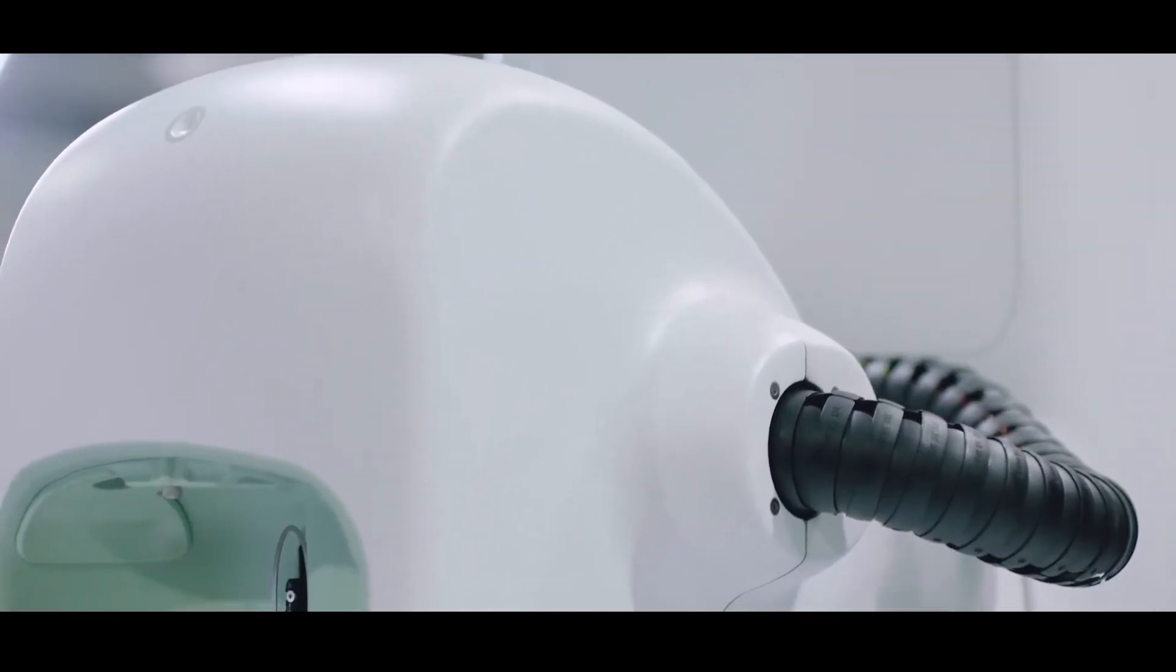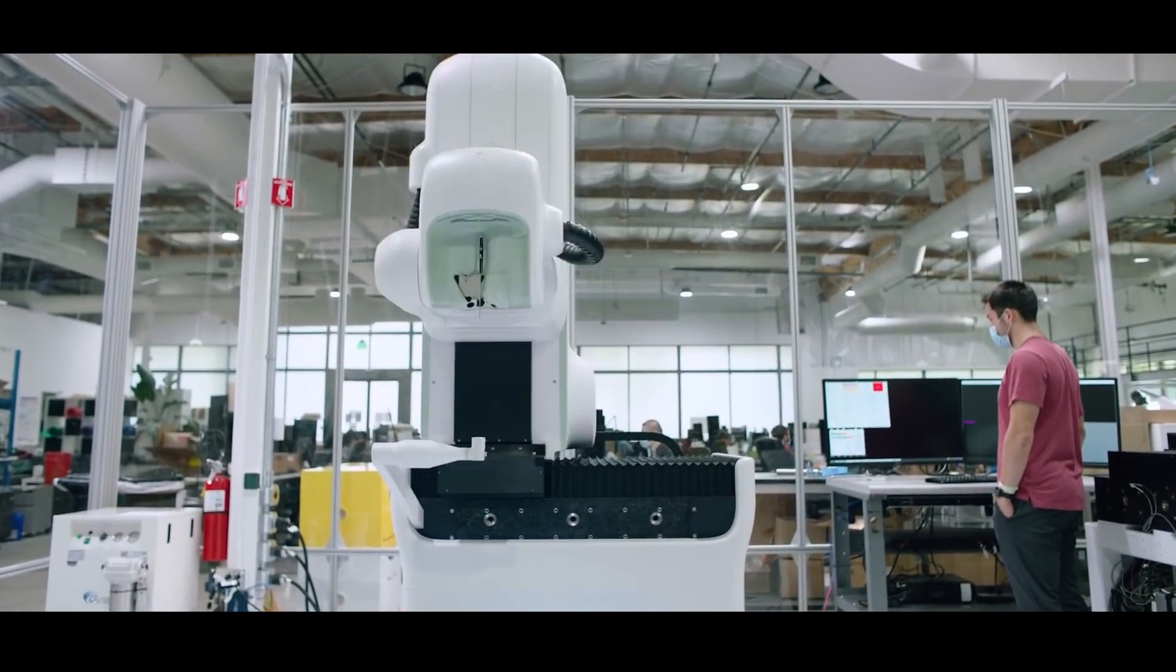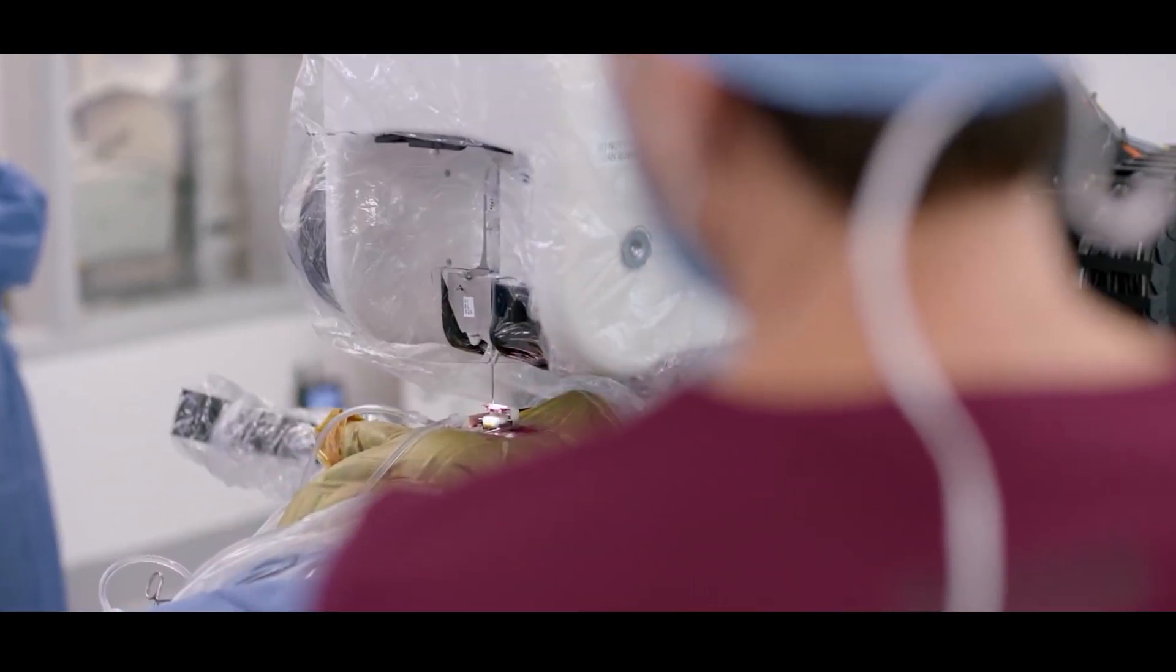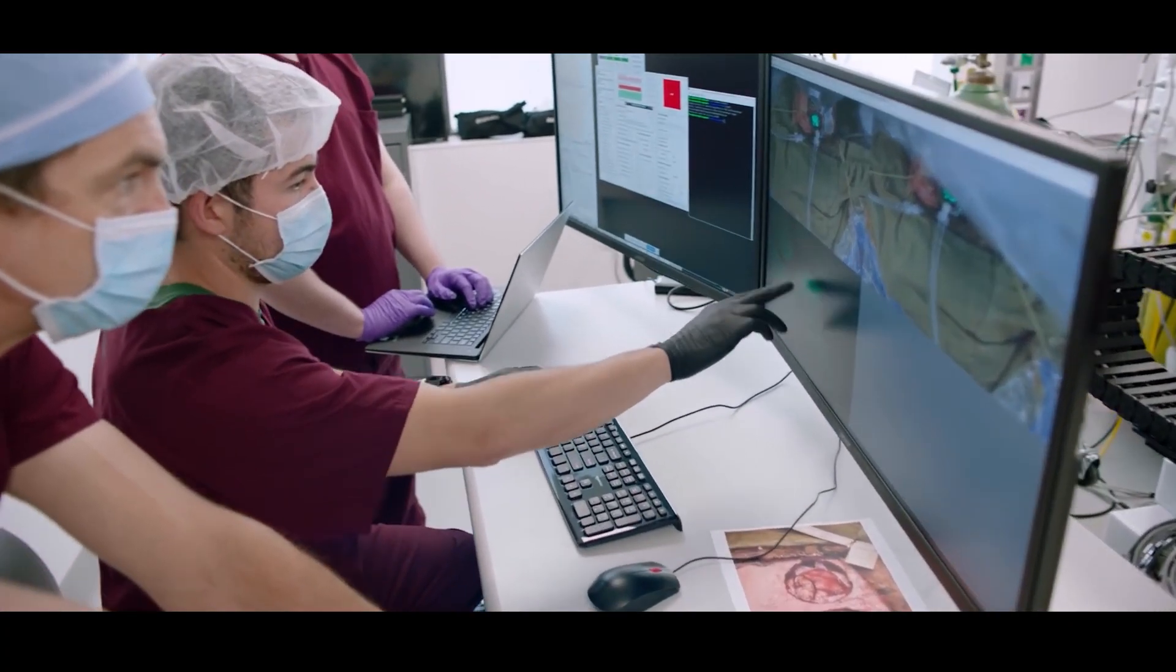Neuralink has spent the last two years testing different needle tip designs. Their in-house laser milling process lets them iterate a new design in less than an hour, milling one needle in just six minutes with a 91% success rate.